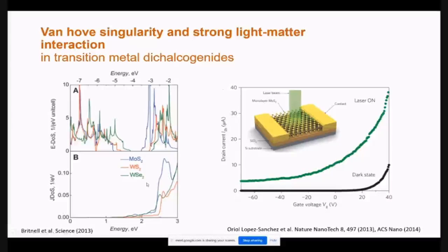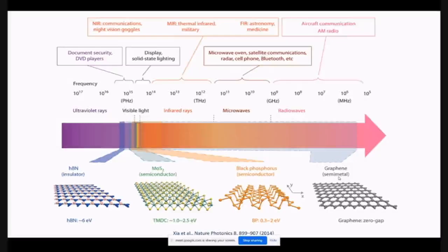Okay? So as a result, if you shine light, there is a huge response in current, and that has been used for various purposes. And because you can get a large number of these materials over a very broad bandwidth, you can cover a very large range, nearly 12 to 15 orders of magnitude of frequency, in which you can sensitize these materials. So this is why there is a lot of interest in light matter interaction with this material. Okay, if that is not enough, what we have been working on is what you call the van der Waals Lego, in which you put one material on top of each other.